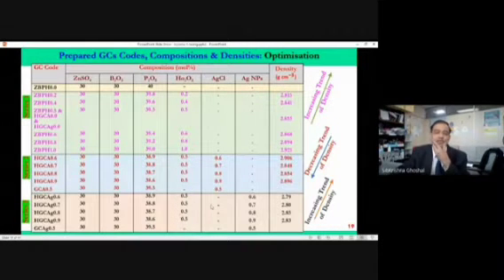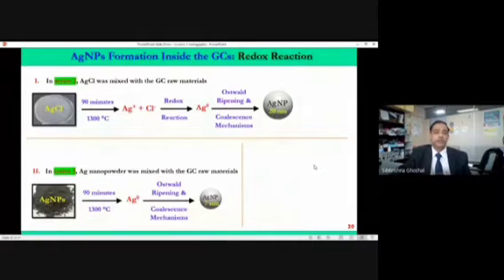So here are the 3 series of glasses and their properties. We have noticed that if the glass does not contain any nanoparticle, only rare earth, density increases. Then the second series contains silver nanoparticle, where silver chloride goes to silver nanoparticle, and density is also decreasing, and again if we put in the pure nanoparticle, density is again increasing. So this clearly indicates that the glass ceramic properties are changing whether we are playing with pure nanoparticle or silver chloride. So that's the most important thing.